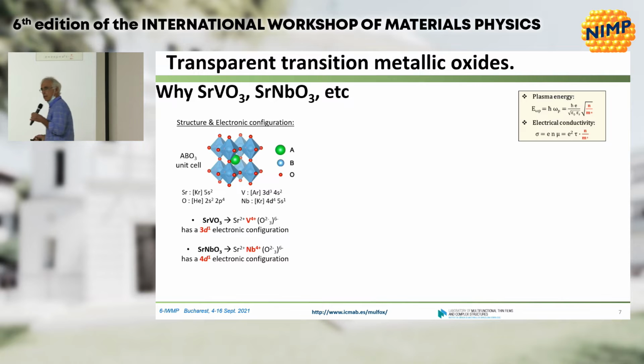Why is strontium vanadate a metal? First, it's a perovskite. We would have this electronic configuration, strontium 2+, vanadium 4+, and that means that you have one electron in the d band. So this material has one electron in a t2g band, so 1/6 full, so it's going to be a metal. And the same happens with the strontium niobate.